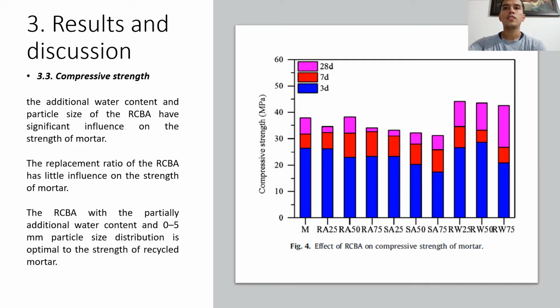Here, the additional water content and particle size of the RCBA have significant influence on the strength of mortar. Additionally, the replacement ratio of the RCBA has little influence on the strength of mortar.